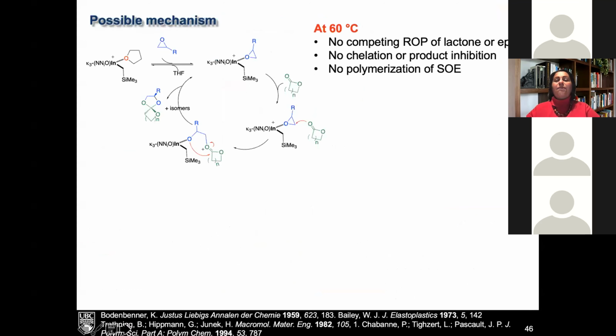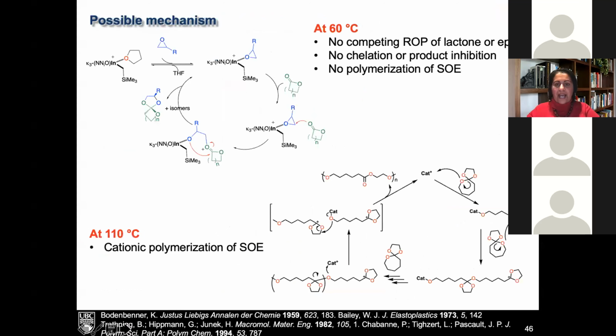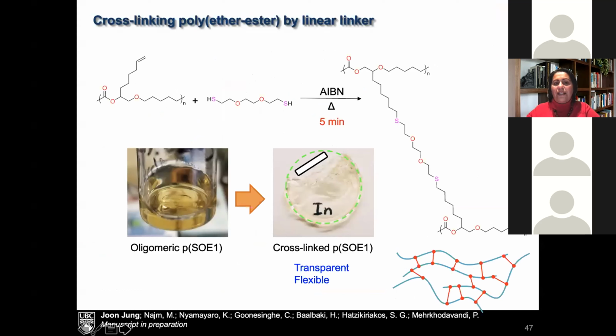I'm not going to go into the mechanism because it's getting late. We can talk about that later if we have to, in terms of polymerization. But one of the things that he's been able to do now, because he has these side chains, is make cross-linked material. And so, for example, if he gets a low molecular weight oligomeric material, and this is probably around 5,000 molecular weight, so it's an oil, it's not really a polymer, you can actually add this cross-linker, and using AIBN radical initiator, actually couple these two. And you can see immediately what happens to this material once the AIBN and the crosslinker are added. You get a transparent flexible film.